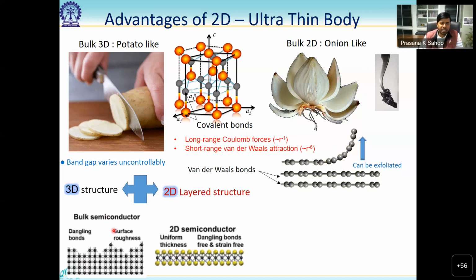In addition, what we can see here in a bulk semiconductor, if you zoom into the surfaces, the surface has a lot of dangling bonds. Dangling bonds are not saturated, because one bond has to connect with several atoms. For atoms on the surface, there are still some bonds that are not completed. So those can be called active sites for other gas adsorbers, or for other things to oxidize. This is like a piece of iron, which can be easily oxidized, not graphite. Graphite is very stable for a long time because the bonds are saturated on the surfaces.